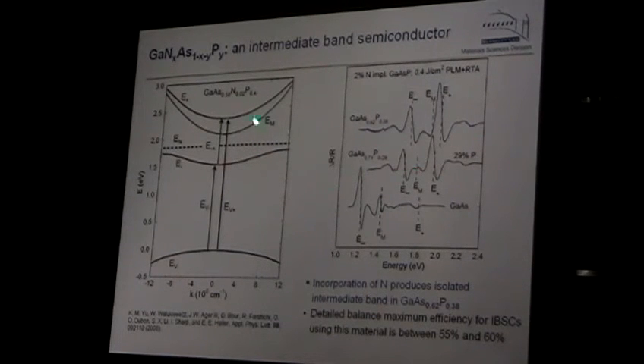This always shows very good. This transition is very strong. So we see the transition from the valence band to this intermediate band, and from the valence band to this conduction band. So these are these transitions. So we could manipulate it the way we wanted, and in fact, this configuration, let's say 2% of nitrogen in gallium arsenide phosphide with, let's say, almost 40% of phosphorus, would be a really perfect system.